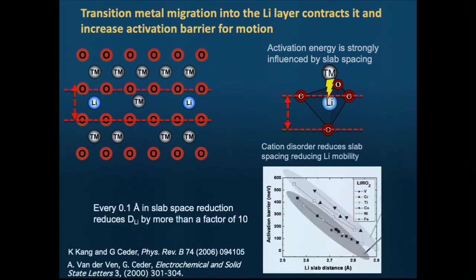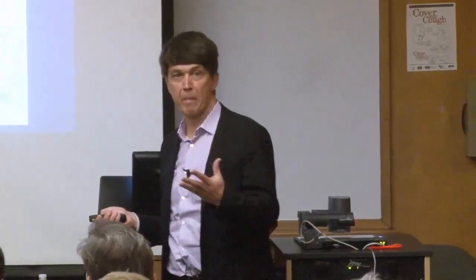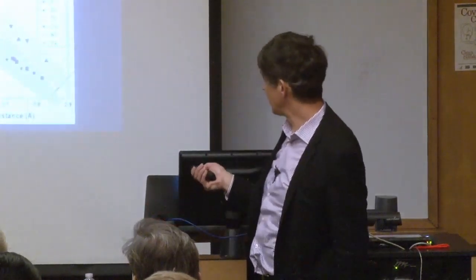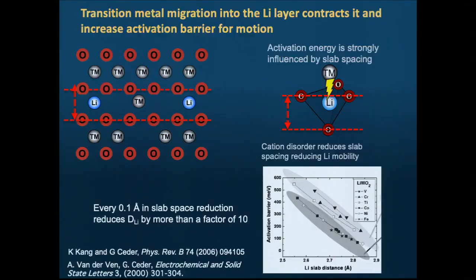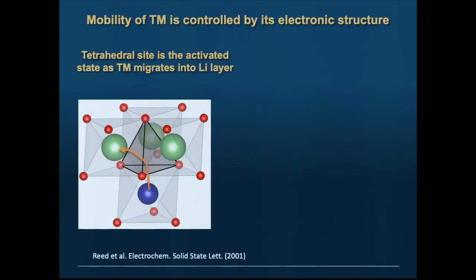You can back that up with ab initio calculations, where we actually can artificially control the slab. And what you see is the activation energy goes up dramatically as you contract this slab. And as engineers, you should learn to appreciate the numbers. If you put something in an Arrhenius factor at room temperature, every 56 millielectron volt causes an order of magnitude of the Arrhenius factor. And here, to get 56 millielectron volts, the slab has to change by only 0.1 angstrom. So you only get a change in lattice parameter of 0.1 angstrom, and you lose an order of magnitude on mobility. OK.